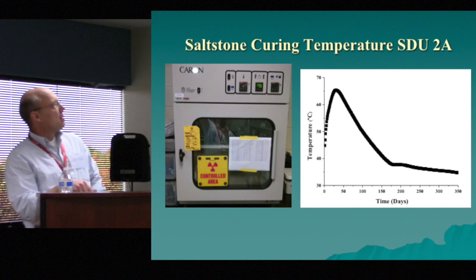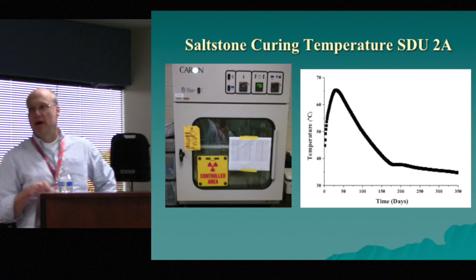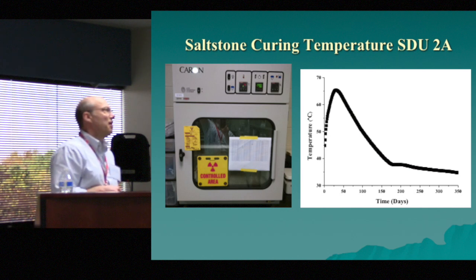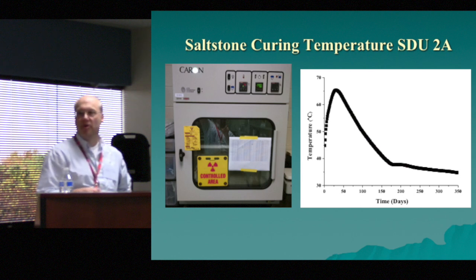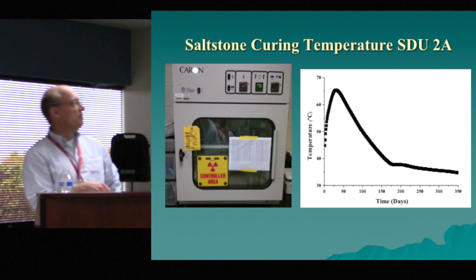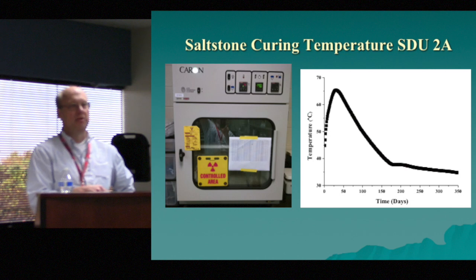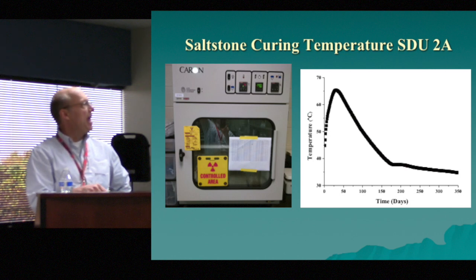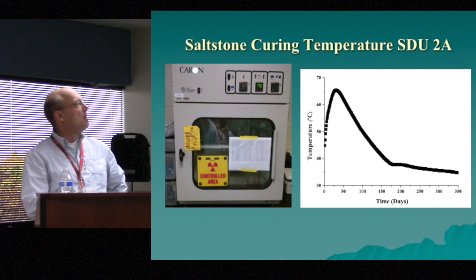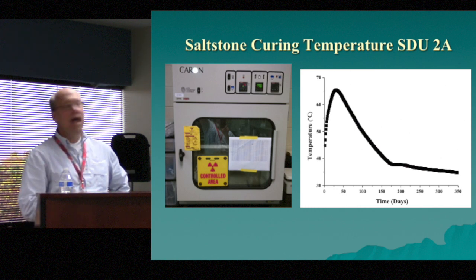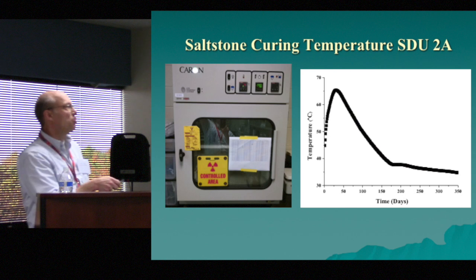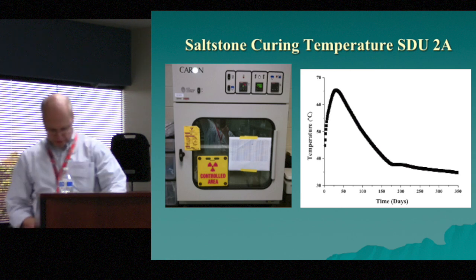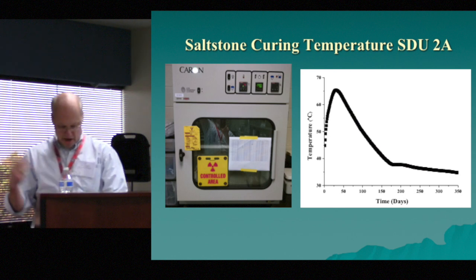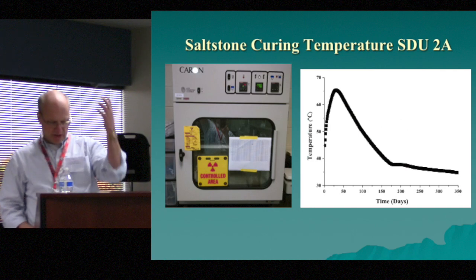So, as Steve was saying, to try to mimic the actual vault conditions, we use these very expensive ovens that are able to both keep a very, very high humidity and a high temperature at the same time. And we try to mimic the temperature of the grout at the extreme actual curing temperatures that we see in the vault and the very high humidity. Next slide.